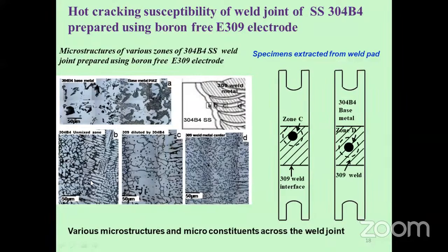We have an unmixed zone, that is, the material is not fully mixed. The base metal is not fully mixed with the consumable, that is, the weld metal. So here we have just the borides, the interdendritic borides, and the austenite dendrites. And slightly inside, in the region of C, we have base metal diluted 309 weld metal. Here the weld metal is diluted by the base metal, that is, boron from the base metal is entering the weld metal.